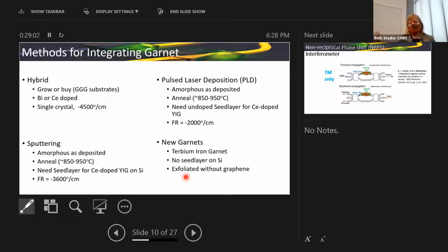Like sometimes we were discussing how films can crack, especially if you have a large area. If all of this was just garnet and you anneal it, it cracks more readily than if you pattern little areas, strip the resist, and then anneal it. Those little areas don't crack as much.